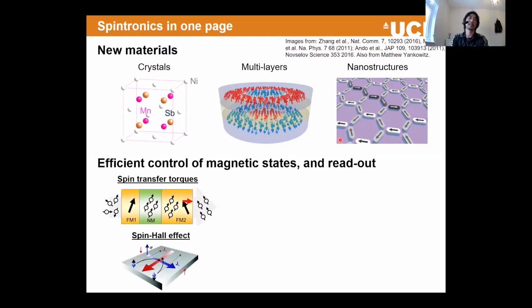And if you make some interesting materials, then we can also control the magnetic moment. So we try to move one of these spins and argue that this is a low energy, no, high energy efficient electronic device based on spin. The popular effect is called spin transfer torque, where you have two magnets here, and by simply passing current through, you can spin polarize the current by using this polarizer, ferromagnet 1. That brings angular momentum to ferromagnet 2, and if this amount of angular momentum is high enough, then you can actually rotate or switch this second layer.